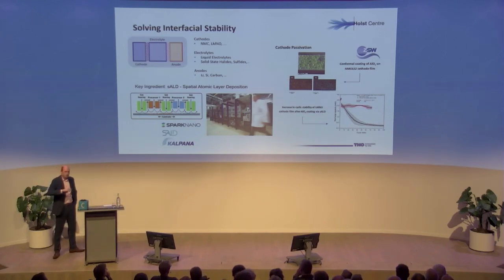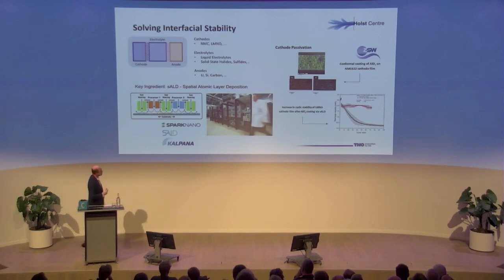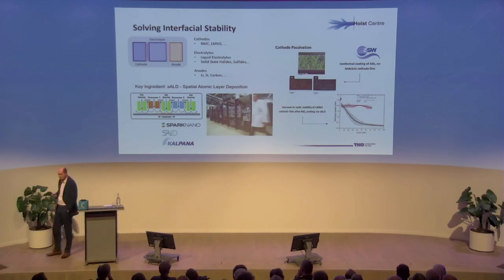And now when you put this little, 2 nanometer layer probably or something, I don't know where it says here, but you put a very, very thin layer of aluminium oxide in, and you can actually make sure that the cycling stability is going to improve significantly. And of course, this is how we want to position the ALD companies into this market.